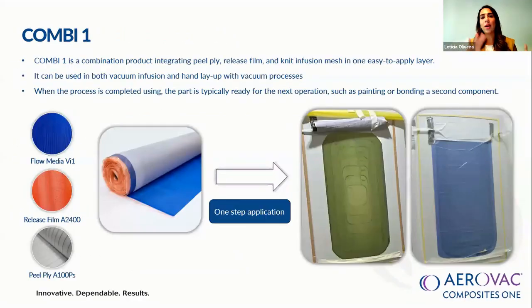Yeah, so here is where you can apply it for repair business, repair wind energy business, but for sure you can use it for other markets as well. This is an example of hand layup with vacuum process after. So you have the Combi One set up in the correct size of your part. When you're doing the repair, in that case it is hand layup, so you know exactly the size of each layer, and you add the resin system.